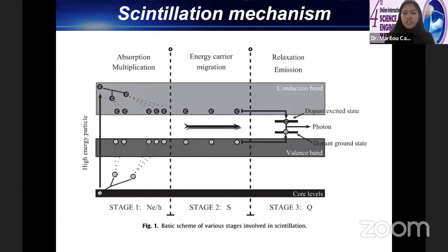So the scintillation works through this mechanism shown in this slide. You have the material that absorbs ionizing radiation or high energy particles, and that creates a hole in the core levels and electrons in the conduction band. When the energies of the electrons become less than the ionization threshold, the electrons and holes thermalize to the bottom of the conduction band and the top of the valence band, respectively. The electrons and holes then migrate to the luminescent centers or the activator ion centers. And when the electrons recombine with the holes, photons are emitted. It's these photons that we see as luminescence and we detect as scintillation light.